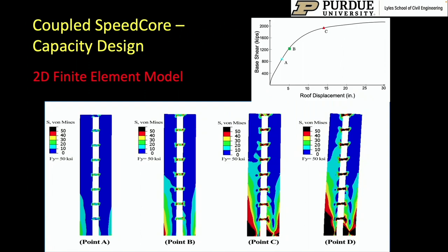And I'm not going to talk about the details of all of those, but I'm showing you here the pushover behavior that I get from a 2D nonlinear inelastic finite element analysis of this coupled core wall system. And again, point A corresponds to the ELF level load. Point B corresponds to the spread of plasticity along the height of the structure in the coupling beams. And point C corresponds to the formation of plastic hinges at the base of the walls. So we get that behavior that we had programmed into the system using the capacity design principle.